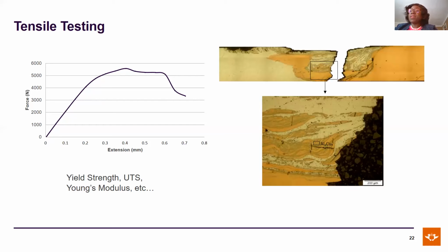In this example I've shown you here, you will see where this particular tensile sample has fractured in the TMAZ. These fractured samples were further characterized, and it was found that this friction stir welded aluminum and copper has some intermetallics, and the intermetallics made the weld brittle, although further details later revealed that in most of the welds produced in this study, the intermetallics had very low peaks. However, they still made the weld brittle. Hence, they are not good for structural applications, as the case may be.